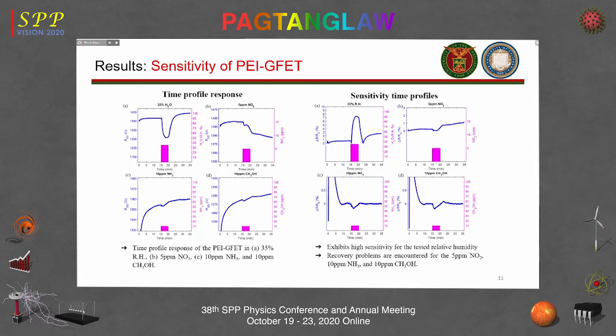In the initial results, when we turn on the humidity gas, the sensor responds very nicely and returns to its original reading when turned off. However, for the gases we were targeting — ammonia, NO2, and methanol — while the sensor does respond with a change in resistivity, it does not recover as fast as for humidity and there is some drift.